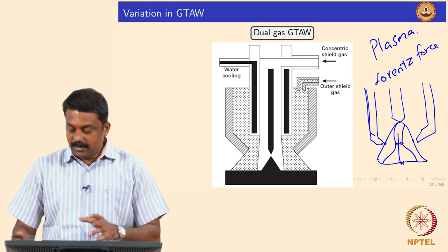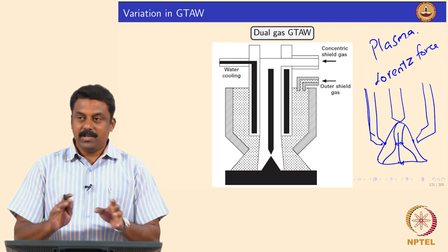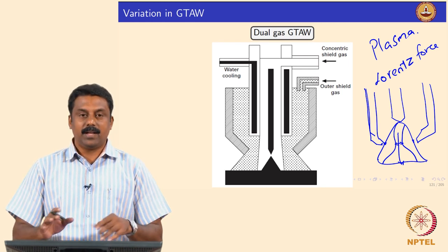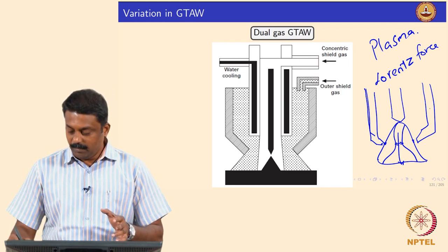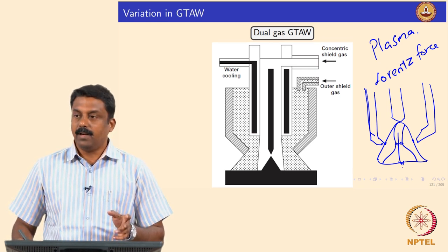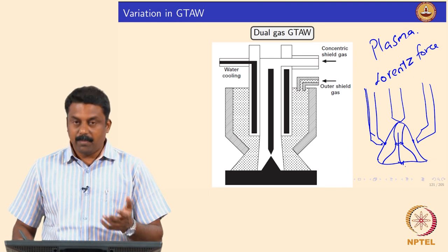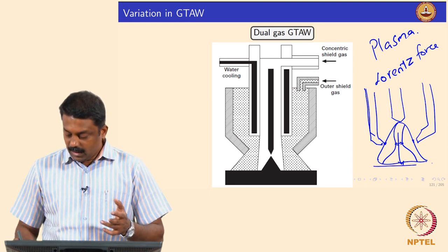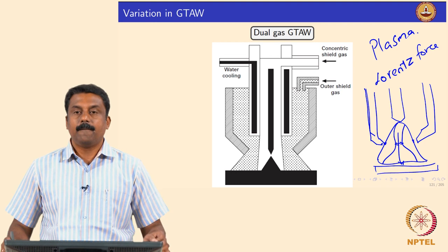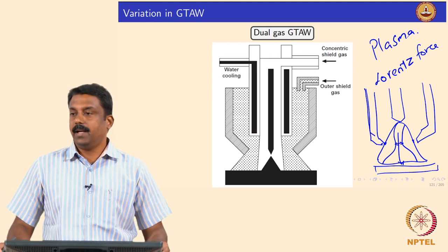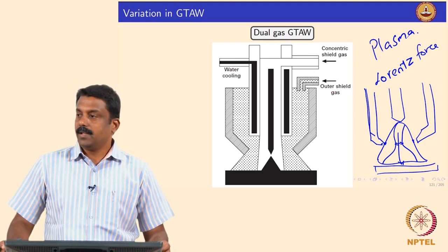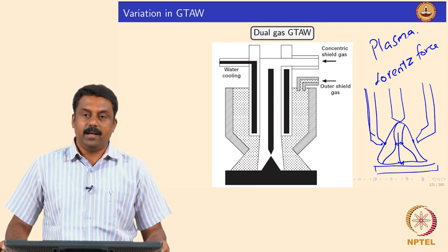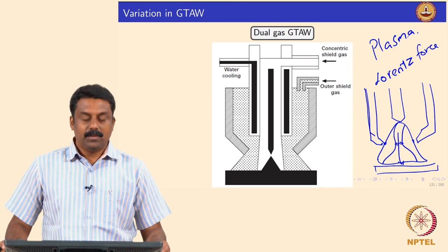So that means that without changing anything, without changing the arc energy, current, or voltage, by just using a simple cooling mechanism, we can increase the plasma jet formation and velocities. And by doing so, we can achieve a very high penetration, a very high arc energy. Yes, it's clear. So the trick is very simple.